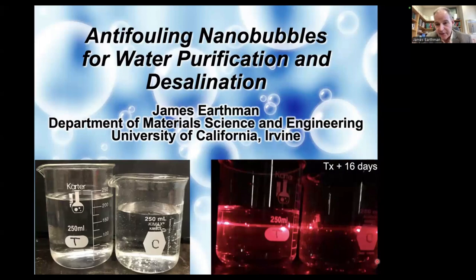And so after 16 days, you can do the same thing. And lo and behold, you can still see that trace. So the nanobubbles, one characteristic about nanobubbles, very interesting, very useful, I think, is that they persist for a long time. Some people have even claimed months, and I've seen evidence of that too with some of the nanobubbles we create. They are very, very stable in water, and they're not that buoyant. Their motion is primarily determined by charges in the water, and we'll get into that a little later.